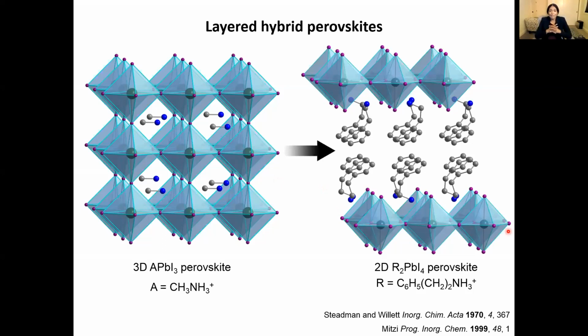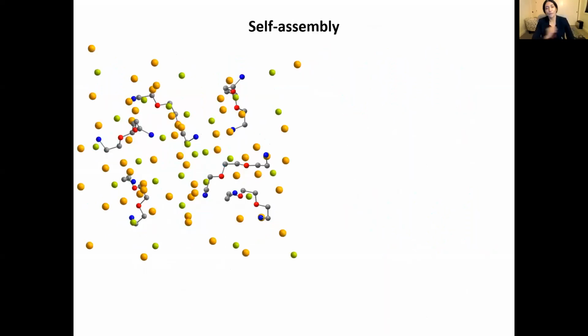So my favorite aspect of these materials is how they form. When I was an undergraduate, I worked with oxide perovskites, which are forged in a furnace at 1500 degrees over the course of a few days. In contrast, the halide perovskites form in a pot of water at room temperature. So these materials form through a process called self-assembly, which simply means that the ions in solution do what they want to do. So if I were to take a pot of water and throw the organic and inorganic precursors to a perovskite in, you can imagine in solution, there's this crazy mess.